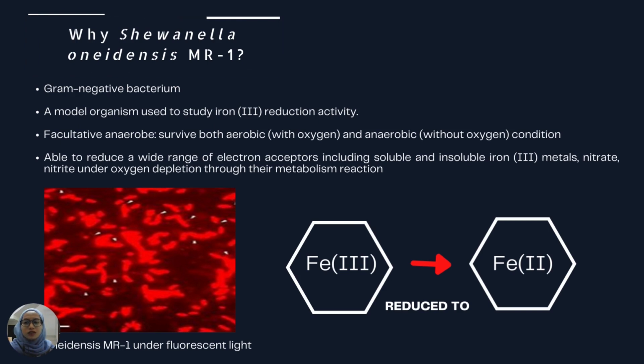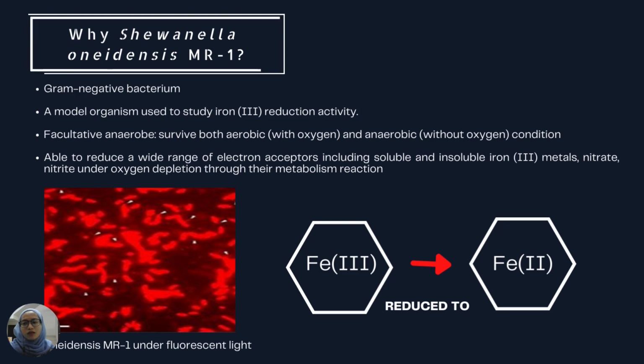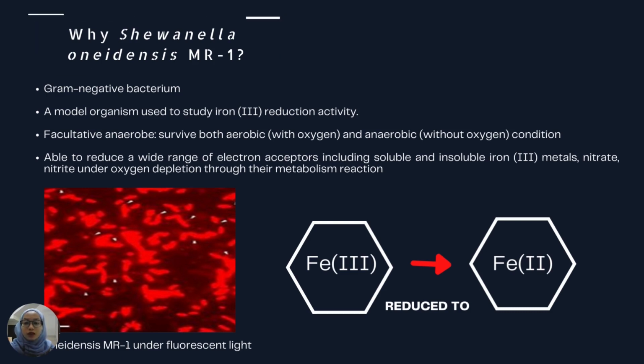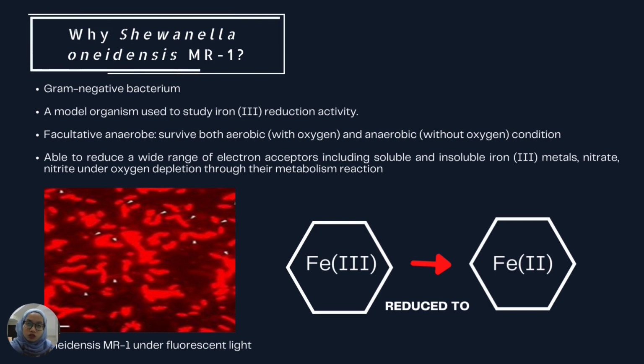But iron-reducing Shewanella is also postulated to inhibit MIC by transforming insoluble iron-3 oxides to other iron-3 or iron-2 substances such as magnetite, hematite, and vivianite, which serve as a physical barrier within the microbial biofilm formation against corrosion under anaerobic conditions. So this would be our main research gap: to investigate Shewanella MR-1 on metal corrosion.